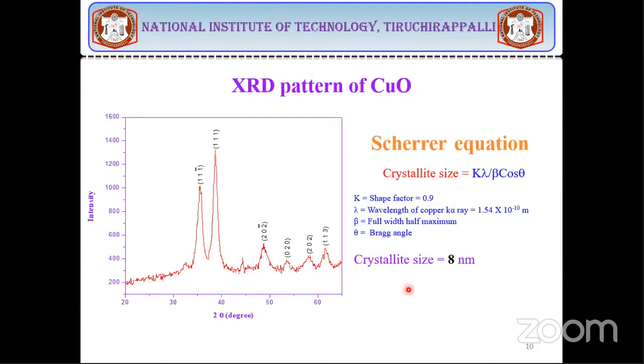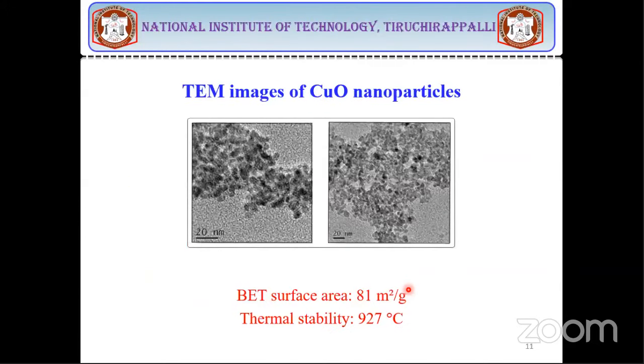After the preparation of copper oxide nanoparticles, though they are prepared by a known method and it's a well-known nanoparticle, we characterized the material just to confirm that we had obtained the correct copper oxide nanoparticles. The crystallite size of the copper oxide that we prepared was found to be 8 nanometers, and the XRD pattern matches with the JCPDS data. TEM images showed that the copper oxide nanoparticles are highly dispersed and spherical in nature. The BET surface area of the copper oxide nanoparticles was found to be 81 square meters per gram, and this copper oxide nanoparticle is highly stable. Of course, we did not do the reaction at this temperature, but this thermal stability indicates that these nanoparticles can be used as a catalyst in reactions that employ even very high temperatures.